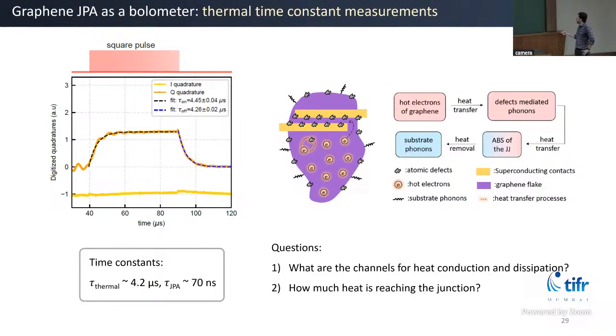So here the two questions are: what are the channels for heat conduction and heat dissipation? We propose this mechanism that there can be atomic defects at the edges which are responsible for the cooling of the junctions, which is why this is slow, about 4 microseconds. Otherwise, the electron-electron cooling timescales are much faster, in picoseconds or even femtoseconds.